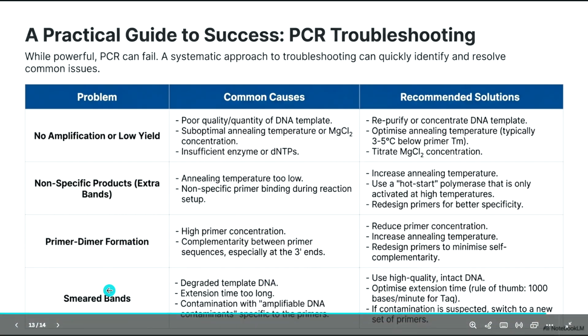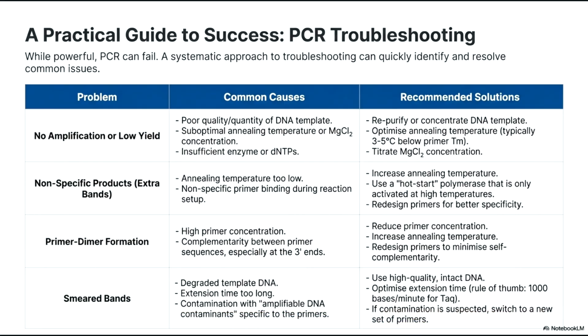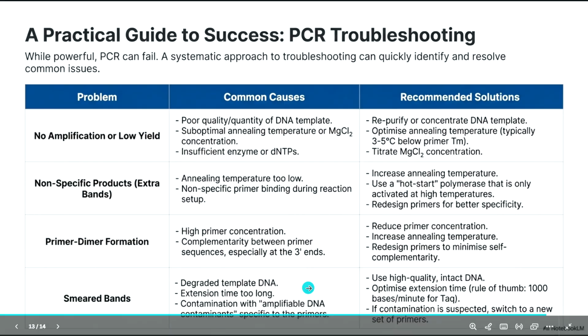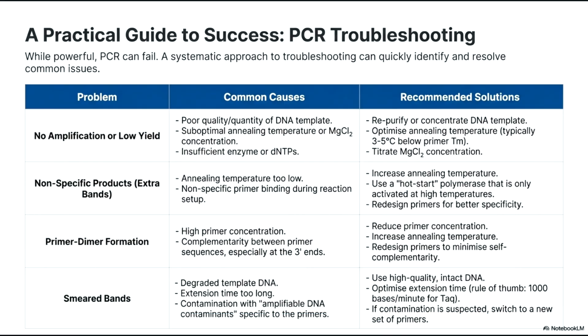Then another problem often seen in labs is the formation of smeared bands. For that, the common causes are degraded template DNA, extension time too long, and contamination with amplifiable DNA or contaminants specific to the primers. The recommended solutions are to use high quality intact DNA and optimize extension time. The rule of thumb is 1000 bases per minute for Taq polymerase. If contamination is suspected, switch to a new set of primers.